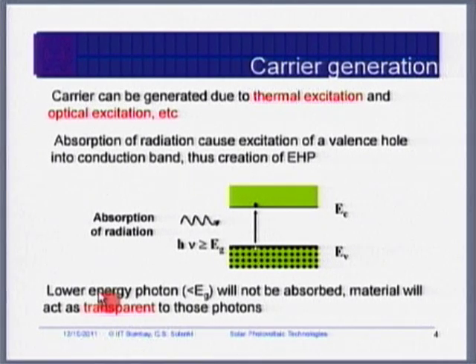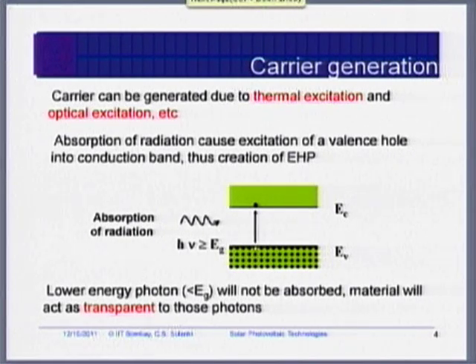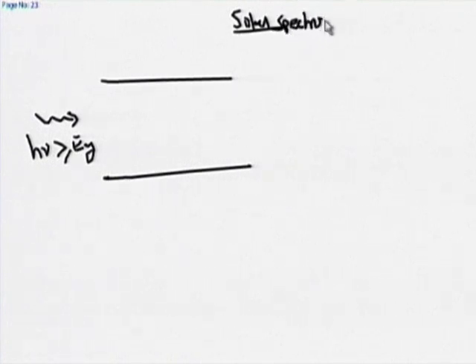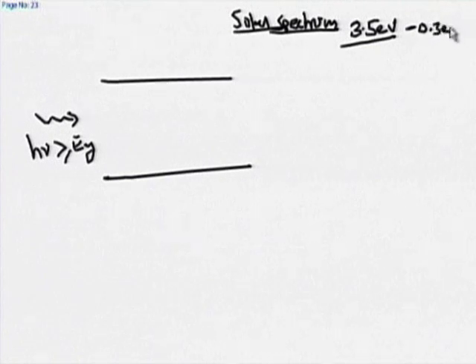The band gap of glass is very high. Photon energy in our solar spectrum varies from the highest energy of about 3.5 eV to the lower side of about 0.3 eV. This 3.5 eV is not enough to excite electrons in silicon oxide, so all photons get transmitted through glass. This gives us an important signal: the incoming photon should have energy hν equal to or greater than E_g.